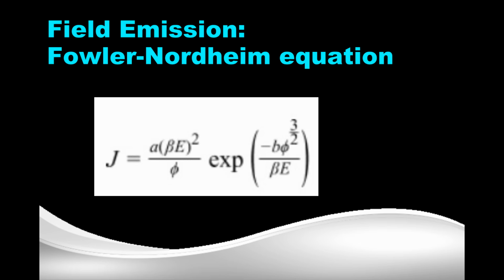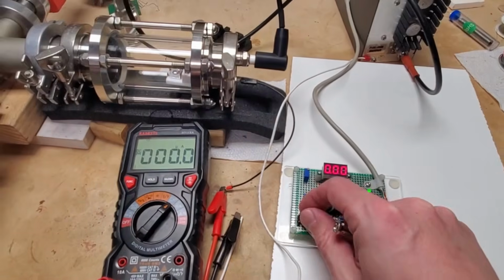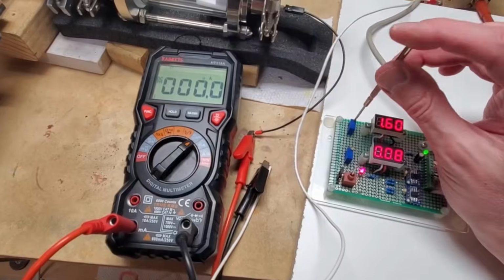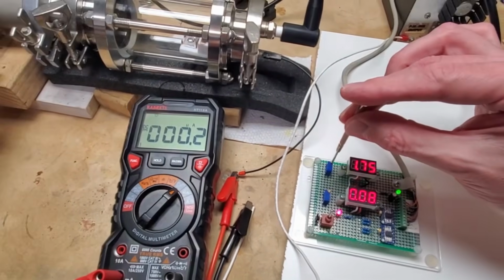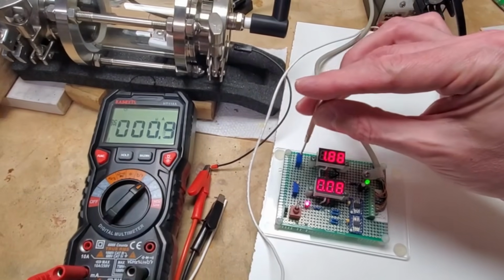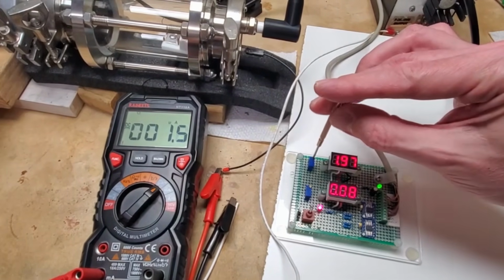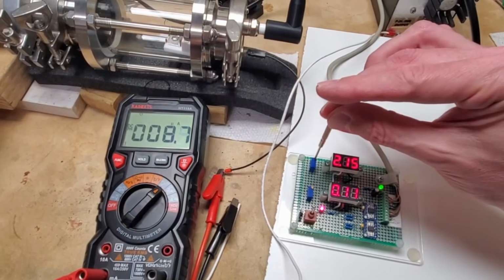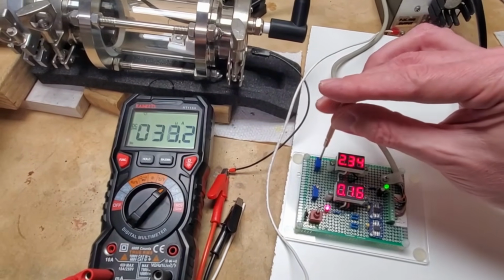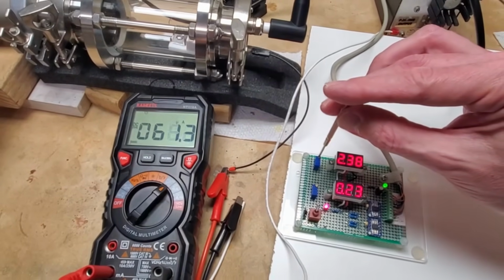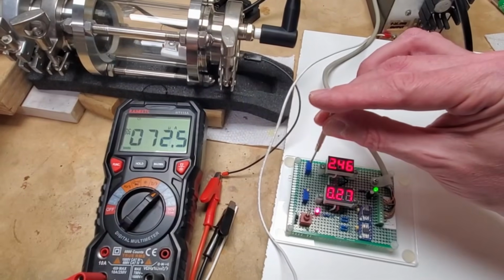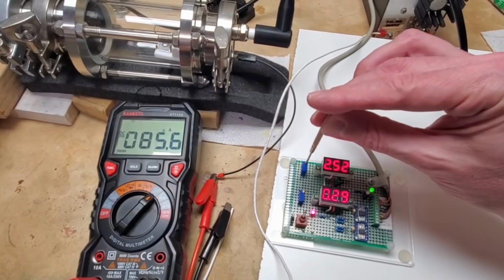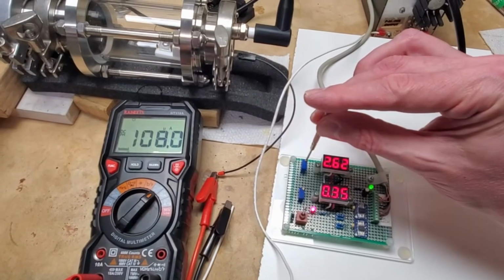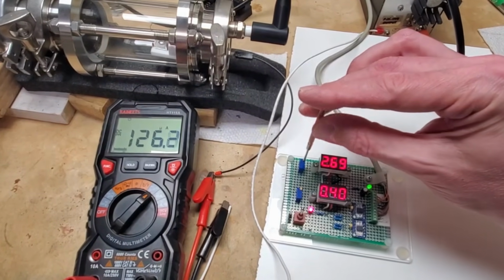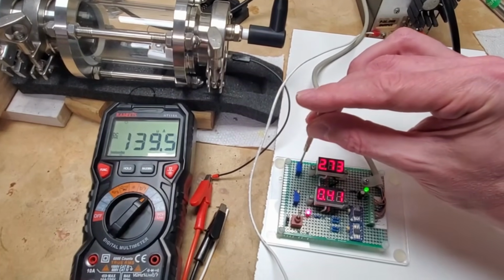The current density of CNT emitters is described by the well-known Fowler-Nordheim equation from the field emission theory. One could take the current readings versus the applied voltage for a CNT emitter and calculate all the parameters of the equation. This is a purely academic exercise, though. The most important practical value is the ultimate achievable current density. My humble DIY CNT emitters, which are 1.6 millimeters in diameter, produce between 200 to 500 microamps, resulting in a current density of between 10 to 25 milliamps per square centimeter. According to many research papers, this is a rather average performance, which I guess is not that bad for such a crude DIY electron emitter.